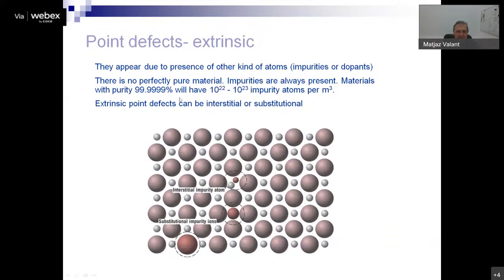Let me just tell you as an example, we would consider a material 99.9999% pure as very pure. But still, such a material would have 10 to 22, 10 to 23 impurity atoms per cubic meter of the material, which is significant. Like intrinsic point defects, extrinsic point defects can be interstitial or substitutional. You see examples here, and of course, because of the different ionic radius of the impurity atoms, a strain field is formed around these defects, similar to what we have seen before.